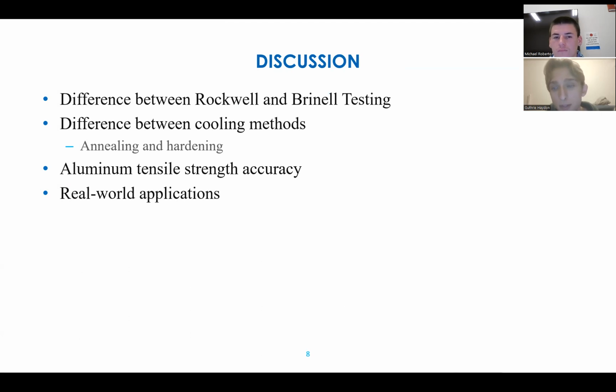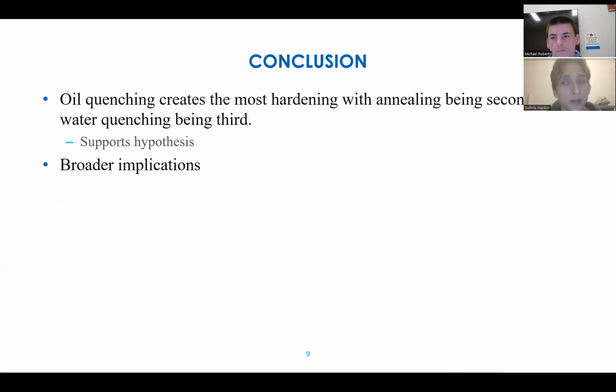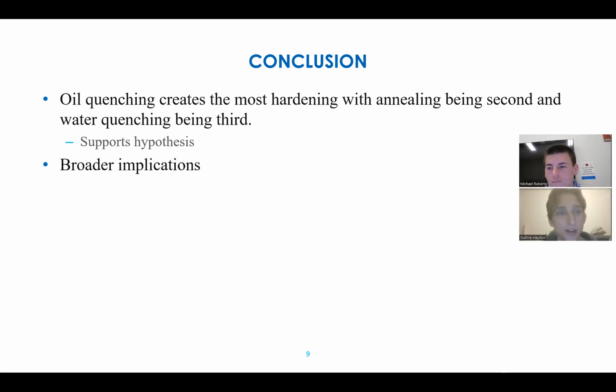So this was really a good combination of a lot of our previous labs because we can understand the various tensile properties relating to the forces, especially a strong downward force that we tested in the lab. And so overall, our hypothesis was supported. Oil quenching creates the most hardening, with annealing being second and water quenching being third. This completely supports our hypothesis.